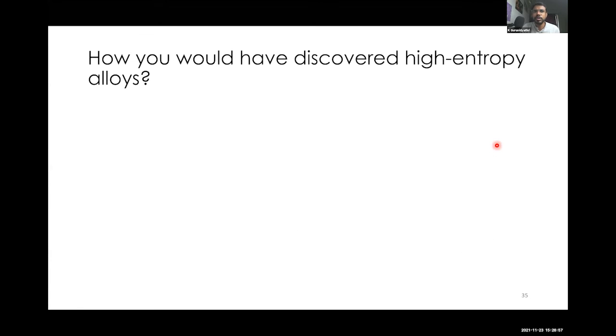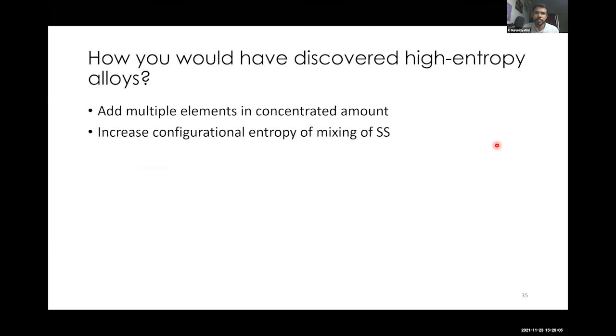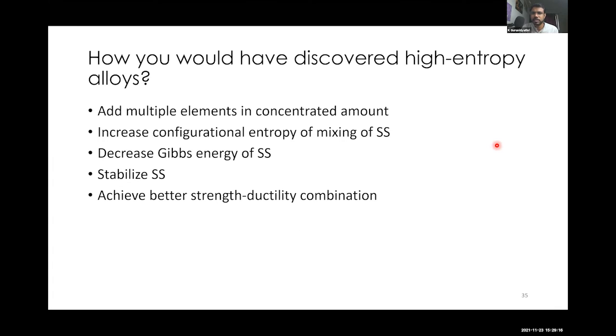So how you would have discovered high entropy alloys is through all this journey. Add multiple elements in concentrated or equal amounts. Increase the configurational entropy of mixing of the solid solution. Decrease the Gibbs energy of the solid solution. Then stabilize the solid solution. Therefore, your strength-ductility combination is better.